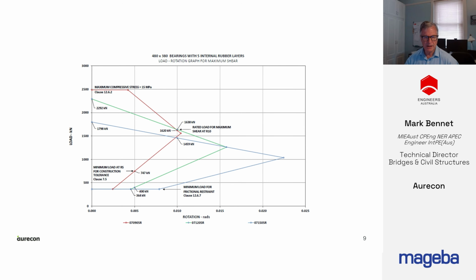This chart indicates the effect of rubber layer thickness on rotation capacity and load capacity. If we are looking at rotations past 0.01 radians, we can see that the 07, 09, 05 bearing has very little operational capacity. If the rubber layer thickness increases to 12 millimeters, there's a reasonable operational area for the bearing performance, and increasing to the 15 millimeter internal rubber layer, you can see the rotation capacities are a lot greater, but the rated load capacity does drop off.